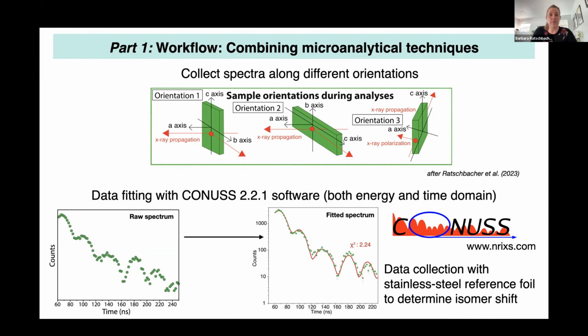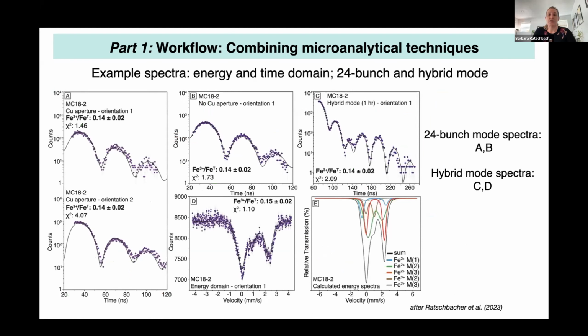We then take the spectra and fit both energy and time domain spectra with the CONUSS software, which is shown here. And we also collected data with a stainless steel reference foil to determine the isomer shift. So here's an example of some of the spectra we're able to collect using energy and time domain and the 24 bunch and the hybrid mode setup.